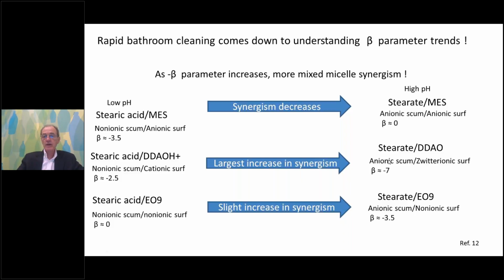And as we raise the pH, we wind up with a system that has an anionic scum, right? Stearate ion interacting with the zwitterionic surfactant. And in that case, the beta parameters are much more highly negative. They can be as far as minus 7 or even greater. So we see that coming down to cleaning the bathroom amounts to understanding mixed micelle synergism in order to solubilize that very insoluble surfactant, calcium stearate.